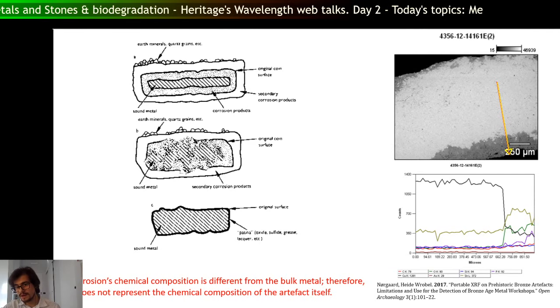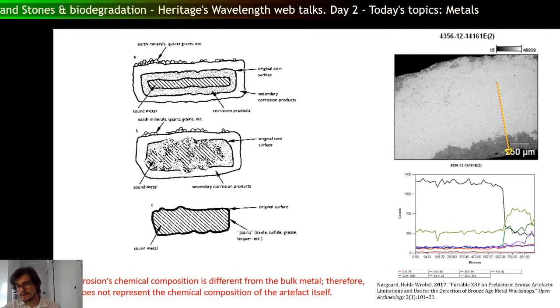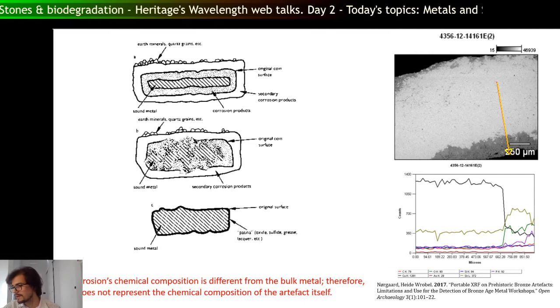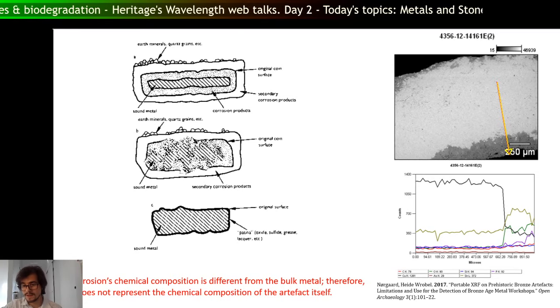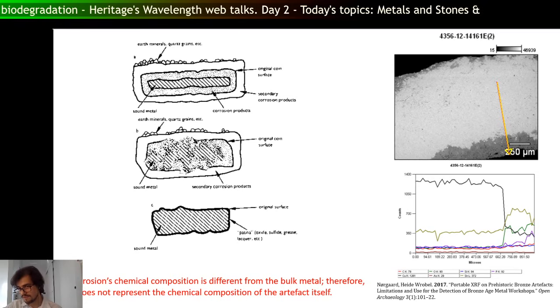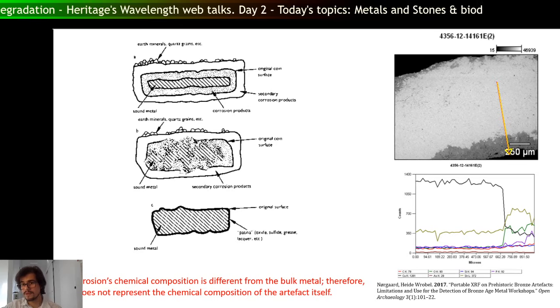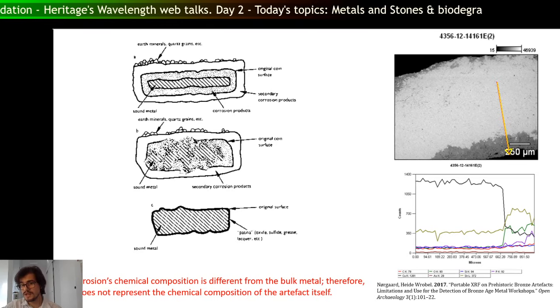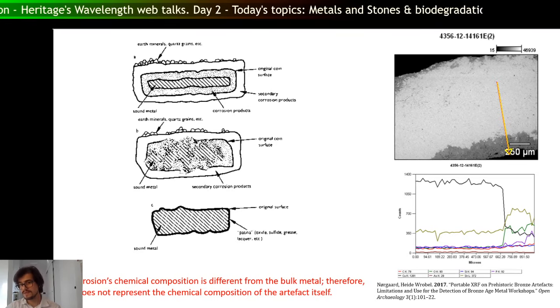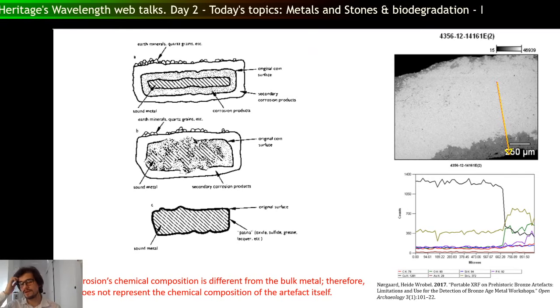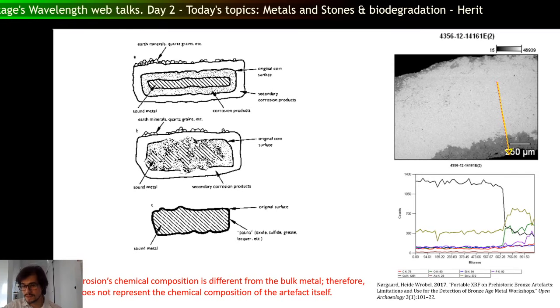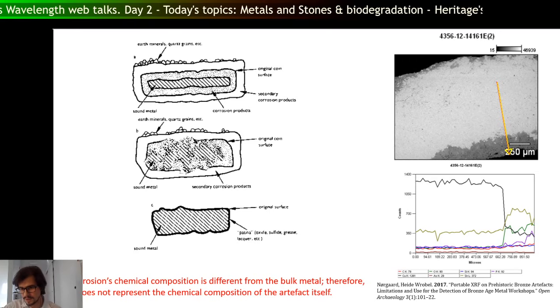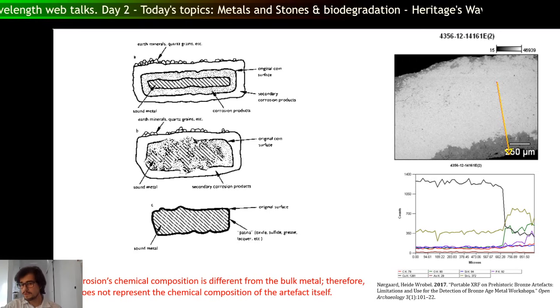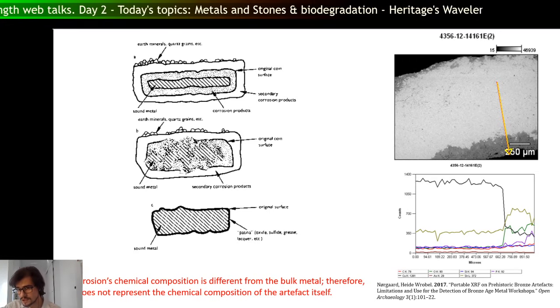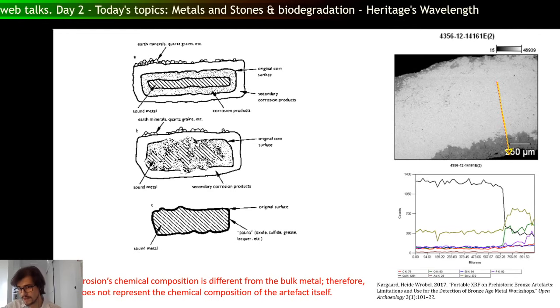And then you can see here on this right picture an arrow showing the direction. Okay, it's so sad that you cannot see my cursor. In the upper part, it represents the 0 point on the graph below, and the arrow goes down. So you can see the chemical composition changing as you move to the outer part of this picture, to the frame, to the border. You can see that the copper concentration, this upper red line, I guess, decreases significantly once it reaches this darker part, which is the corrosion layer.